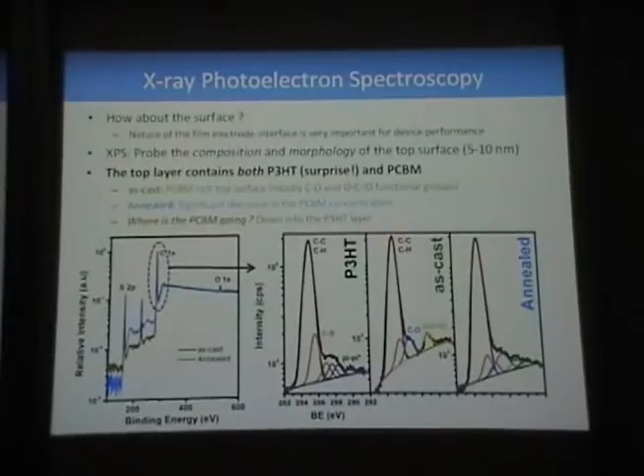Okay, what about the surface? Because the film-electrode interface is very important for device performance. We turn to X-ray photoelectron spectroscopy, XPS, to probe the composition and the morphology of the top 5 nanometers of the device. This is a survey scan from the XPS for the as-cast and the annealed structure. And the surprising thing here is that you get the peaks from the sulfur, and the only material that has sulfur is the P3HT.